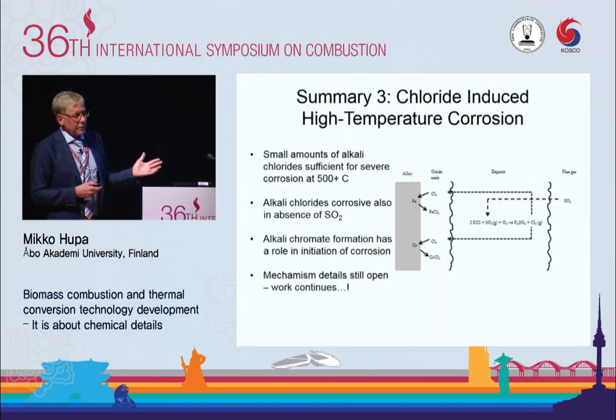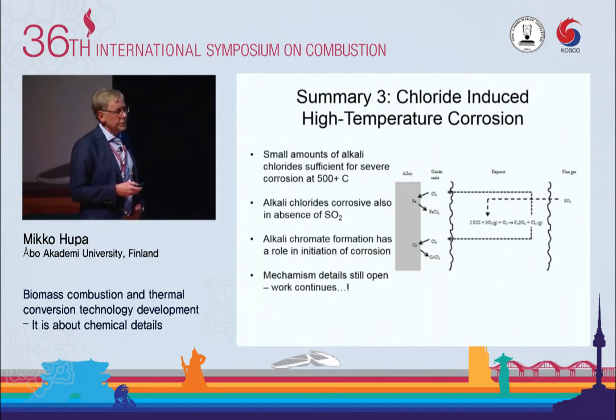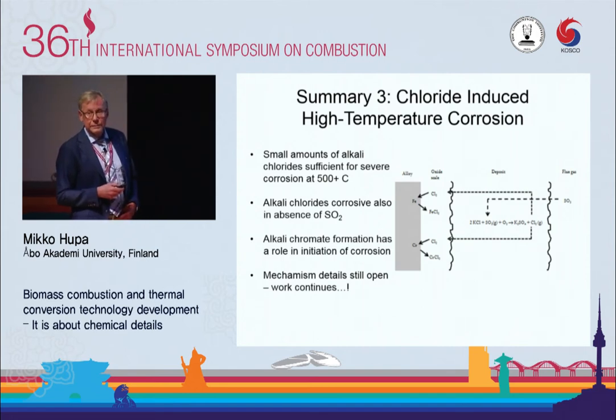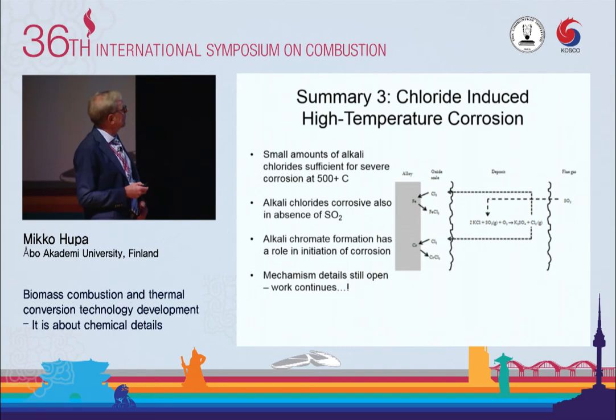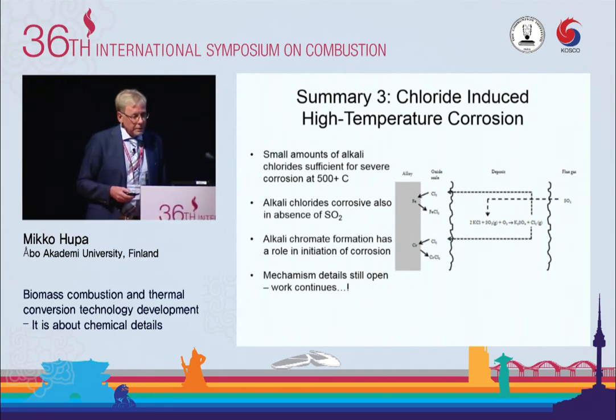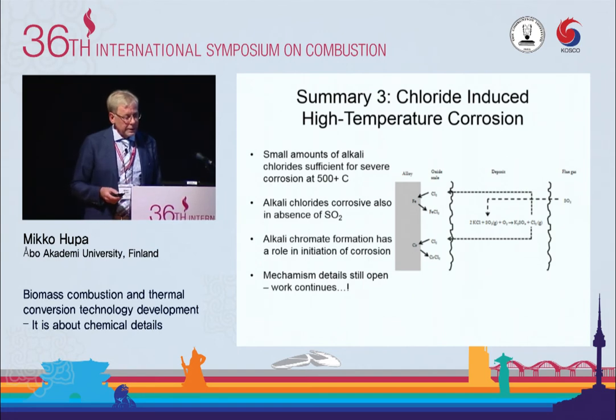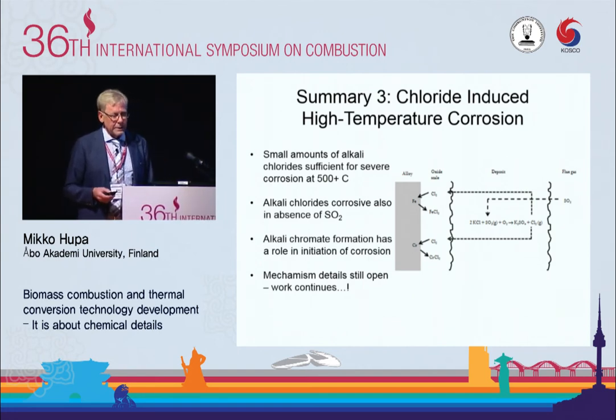Small amounts of alkali chlorides are sufficient for severe corrosion at 500 plus °C. This is one conclusion. Alkali chlorides are corrosive also in absence of SO2. This alkali chromate formation has become an interesting thing. There is work going on. We try to understand a little better why, how, and how that happens.